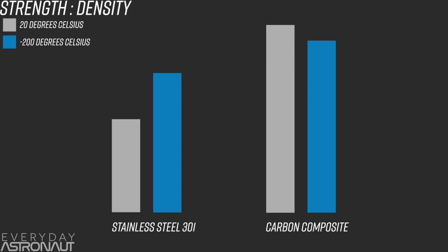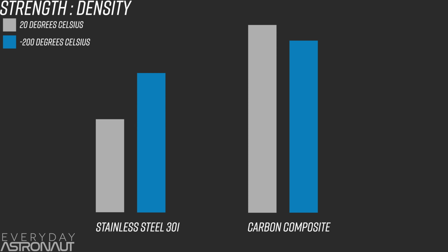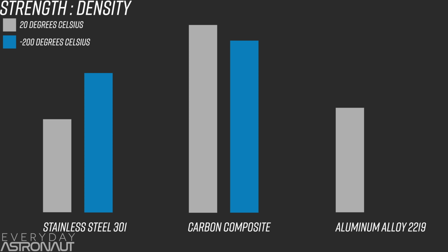And here's where the weight difference can close. And let's throw in aluminum alloy 2219, which is probably similar to what SpaceX currently uses on their Falcon 9 rockets. While we've got this pulled up, I should probably explain it really quick. This is comparing the density to the yield strength ratio. So density best represents weight since it includes volume, and the strength we're showing here is yield strength. Since there isn't a unit of measurement that corresponds between volume and yield strength, there isn't a nice clean number or unit to represent this ratio.